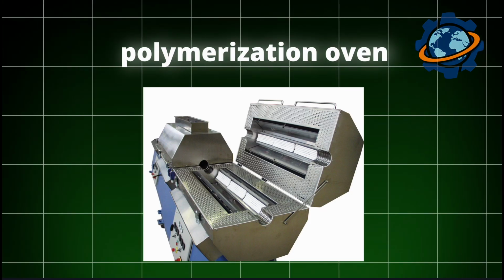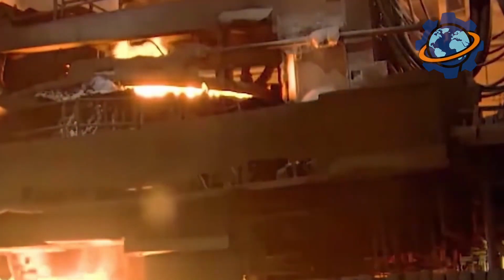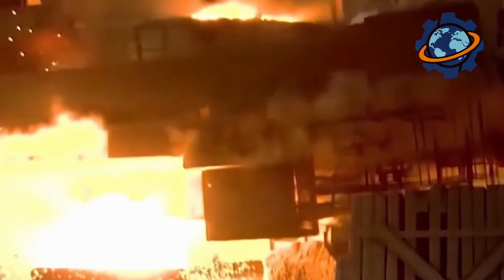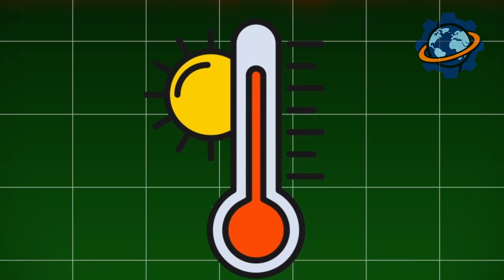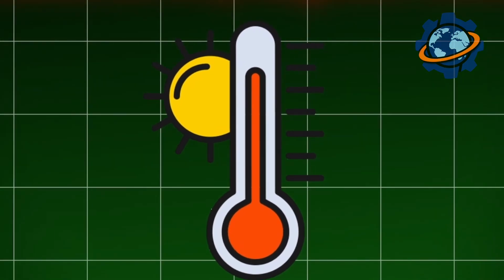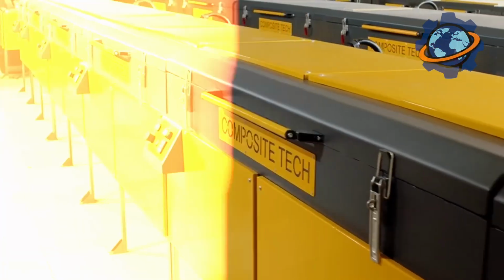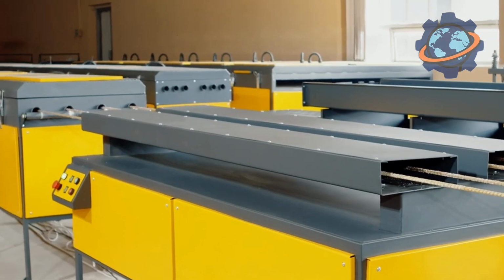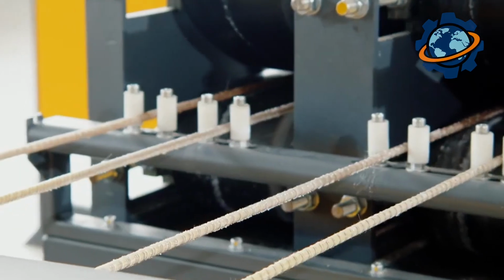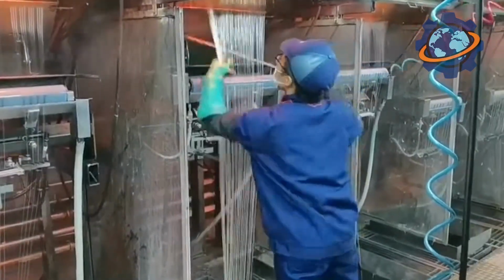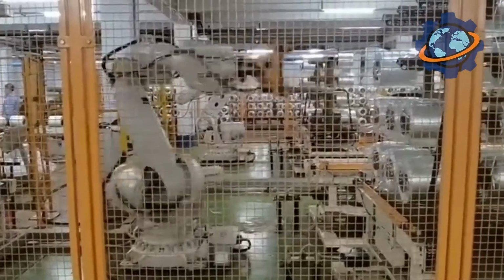This is a long chamber that can extend for tens of feet, inside which a high temperature is maintained, usually 400 degrees Fahrenheit. Here, the final transformation takes place. This is not just drying. Under the influence of heat, the resin molecules begin to actively bond with each other, forming a strong, rigid three-dimensional network. The liquid, sticky syrup turns into an extremely strong and hard composite material that permanently binds millions of glass fibers into a single monolith.